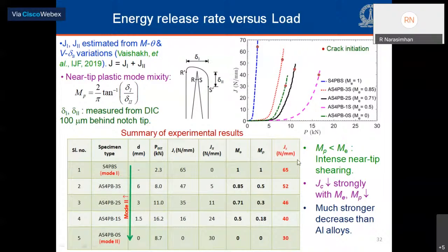So the most important observation from the table is that as we decrease the mode mixity and approach mode 2, the notch fracture toughness diminishes quite extensively, by more than a factor of 2. And also the plastic mixity, the near tip mixity, is lower than the elastic mixity, and that's due to intense shearing which is taking place in this specimen.